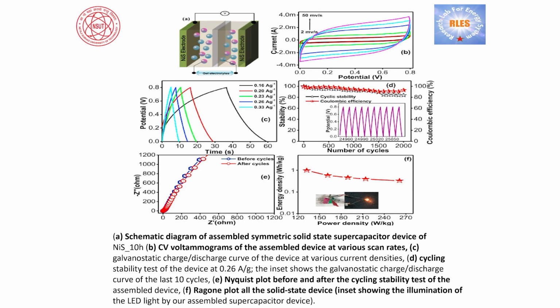CV voltammogram of the assembled device at various scan rates, galvanostatic charge and discharge curves of the device at various current densities, cycling stability test of the device at 0.26 ampere per gram. The inset shows the galvanostatic charge-discharge curve of the last 10 cycles.